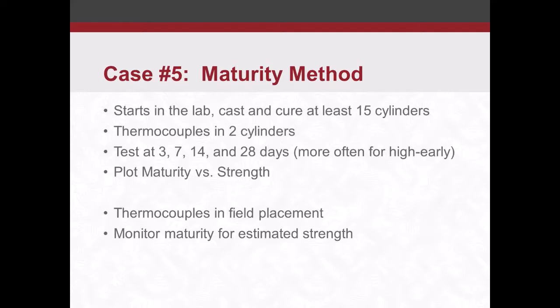So to do the maturity method, there are 2 steps to it. It starts in the lab. You cast a bunch of cylinders. You put thermocouples in 2 of the cylinders, and then all of the cylinders are cured the same way, at the same temperature specifically. Then we make tests at 3, 7, 14, and 28 days, maybe more often if we're looking for earlier strengths. This particular project, we took strengths more often, and we plot the maturity versus strength.